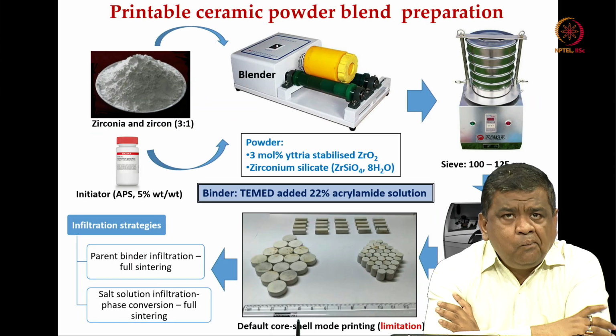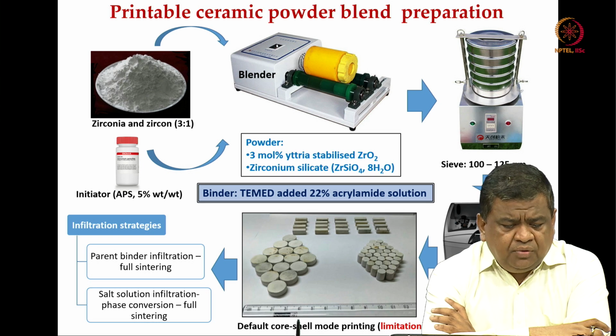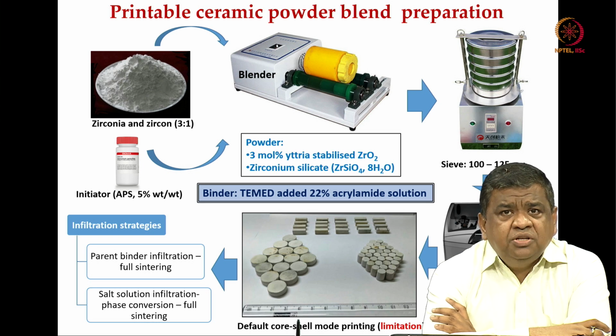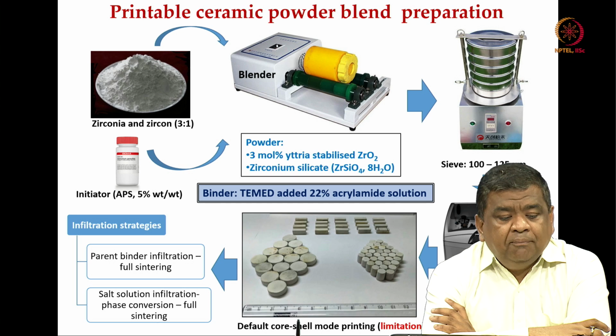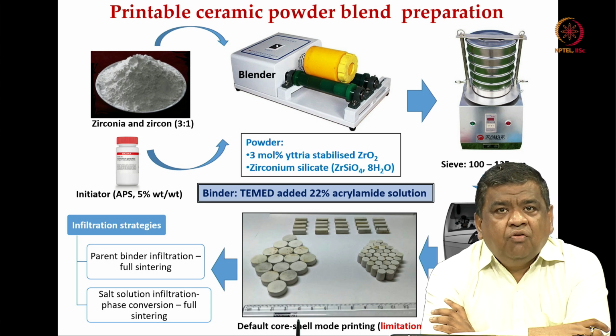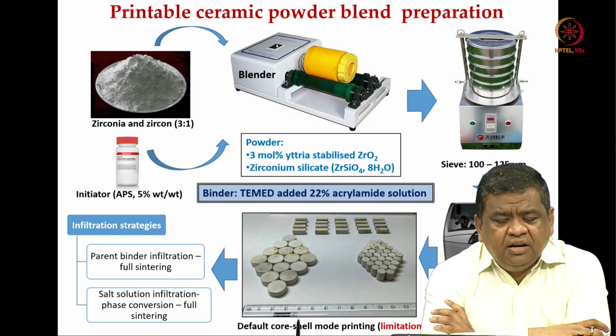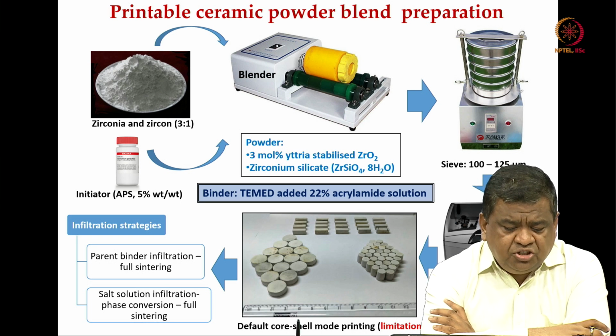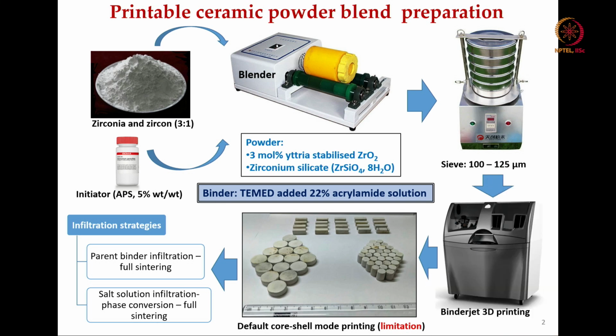What have we done? Initially we started with zirconia itself and then mixed it with the initiator, like the way we have done for the Ti6Al4V, and then the initiator concentration was varied. They were blended, then sieved, and then 3D printed, but we did not get appreciable strength properties and there was significant porosity in these materials. We could not reduce the porosity.